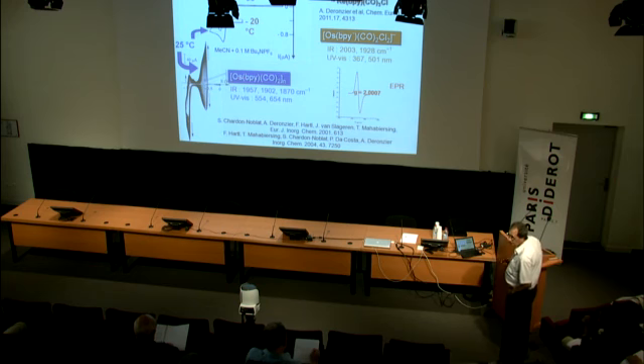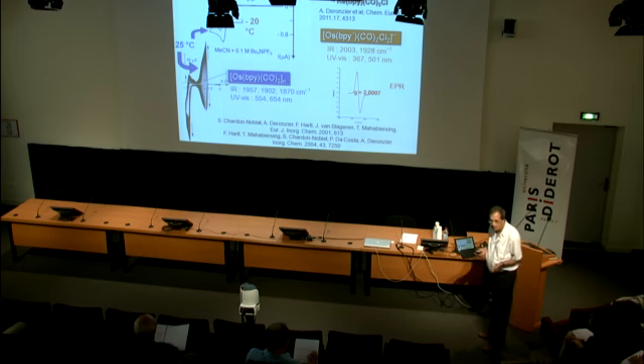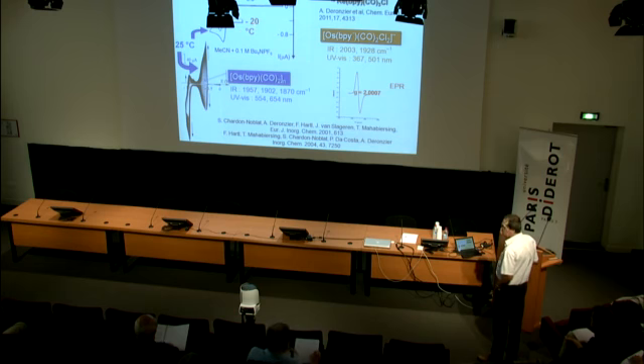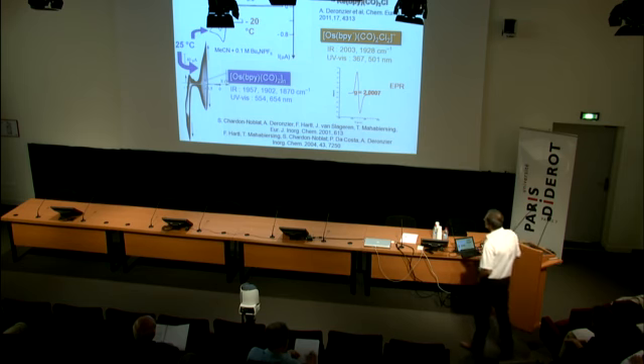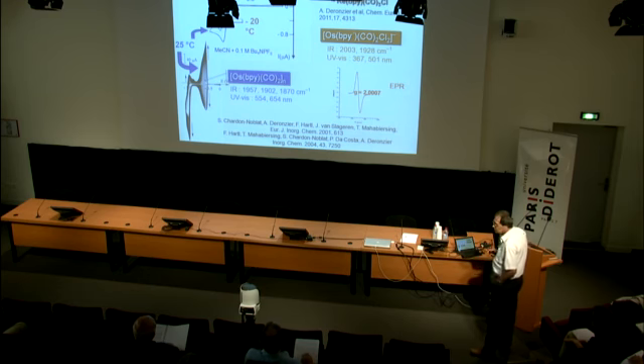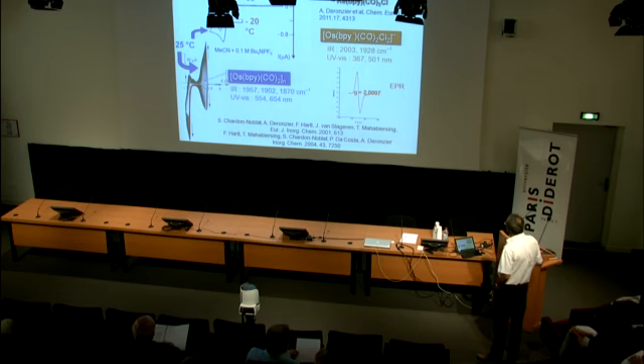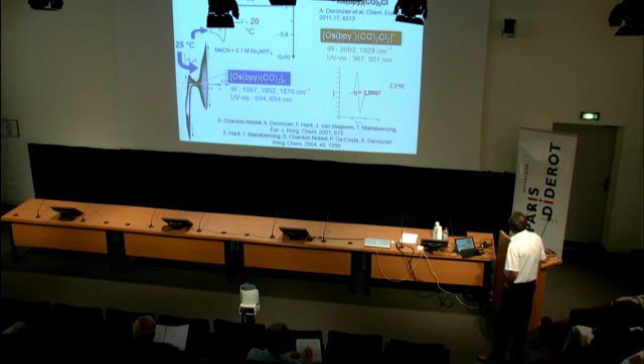That's the typical cyclic voltammogram of the osmium derivative in the same conditions at room temperature. You can easily make the same kind of film as for the ruthenium. But if you use a lower temperature, minus 20 degrees for instance, the room-temperature irreversible two-electron process is replaced by a nice one-electron, reversible electron transfer. And we did some spectro-electrochemical experiments, and we were able to characterize by infrared and UV-visible the corresponding species, the transient radical anion of the osmium complexes, characterized by this typical EPR signal.